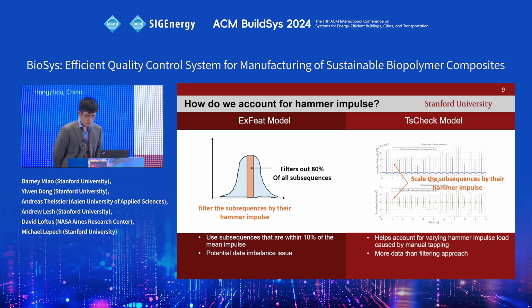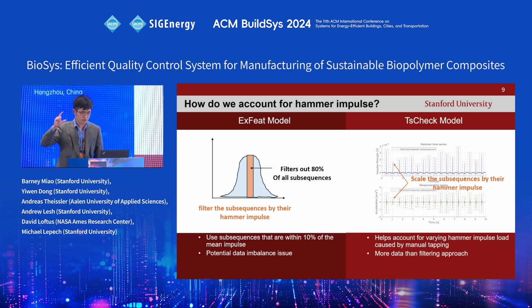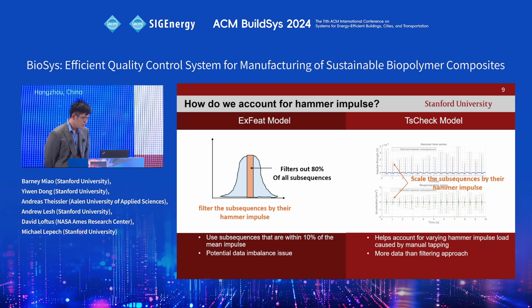One other challenge to note is that because we are manually applying an impulse on the specimens, there is a variance in the hammer amplitude or impact per tap. So in order to account for those things, or it'll be pretty bad if you don't, for the ExFeat model, we would do a filtering approach where we would look at the amplitudes of the force of the impulses. In this case, we would filter out based on whether the impulse is within 10% of the mean force that you measured.